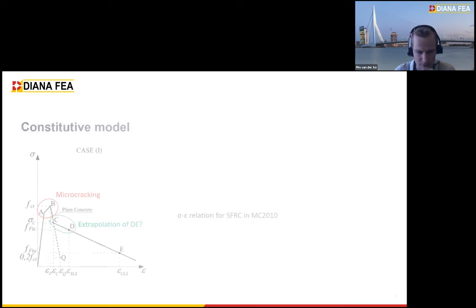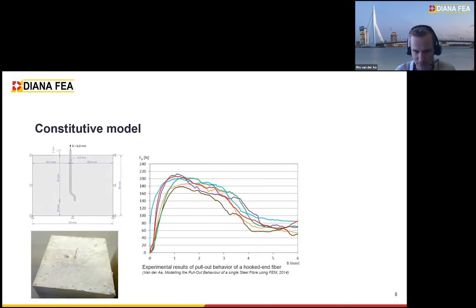we already have the full strength of our steel fibers. If you look at some experimental tests, for example for the hooked end fiber, which is also widely used, you can see that some slippage of the fiber is required to get full strength. In this experimental test, the peak is around 1 millimeter. So in order to reach the maximum strength of a fiber, you need at least around 1 millimeter in this example. Of course, there are other fibers which have a different behavior and could have a peak a lot higher or at least quicker, so that a smaller slip is required to reach your maximum force. However, in this case, I just had a look at the hooked end fiber.